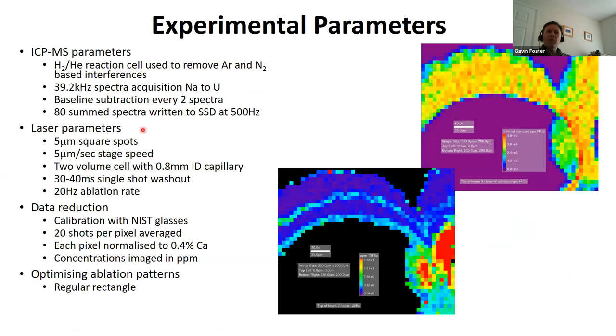The laser parameters were 5 micron spots. We moved the stage at 5 microns per second, so it's slower than what we've seen previously today. We use a two-volume cell with a thin capillary to give us the best washout, and we use a 20 hertz ablation rate. We had to use these sorts of conditions because the variations we're looking at are quite small, and we're actually looking at elements that are ppm level within the test. The foram shell. We calibrated using NIST glasses. And I'm going to present concentrations in ppm.